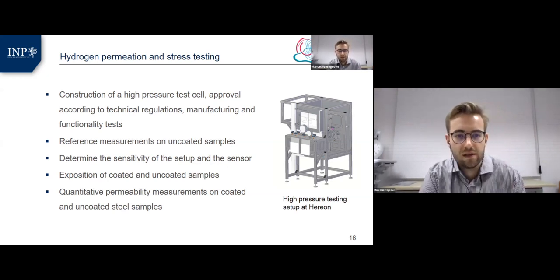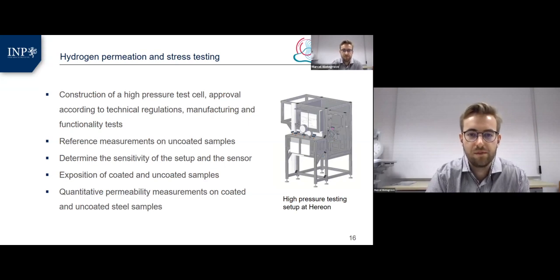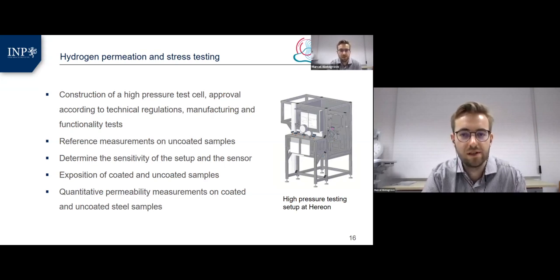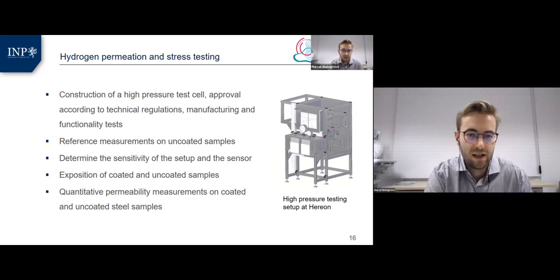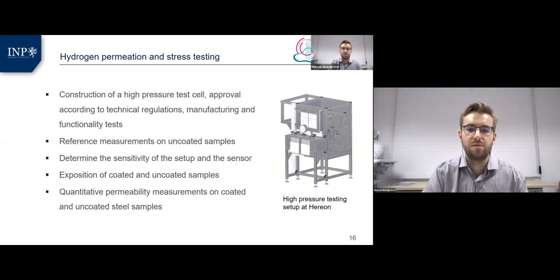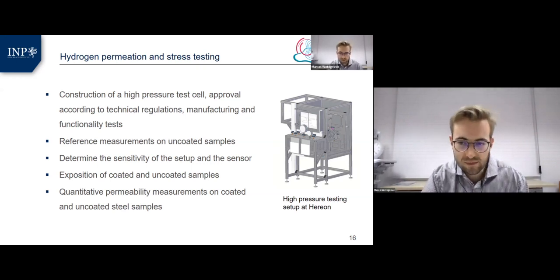And with this, reference measurements on uncoated samples are first achieved to determine also the sensitivity of the setup and the sensor, and to expose coated and uncoated samples to hydrogen. Also, quantitative permeability measurements of coated and uncoated steel samples are possible with the new setup.